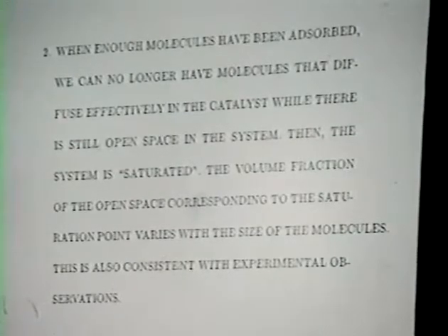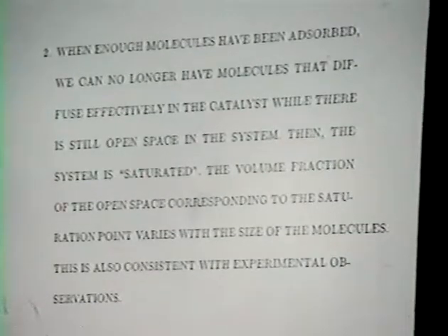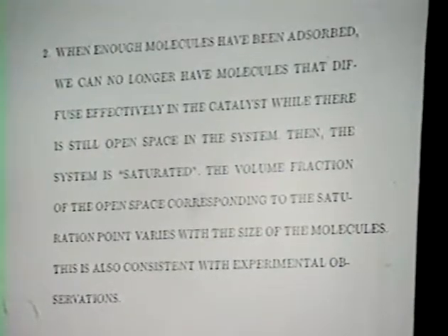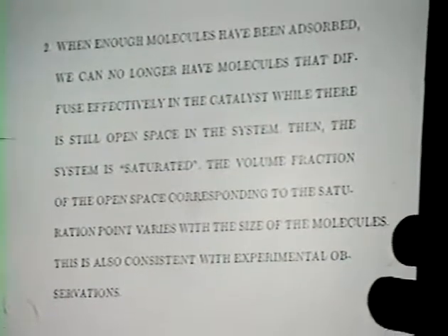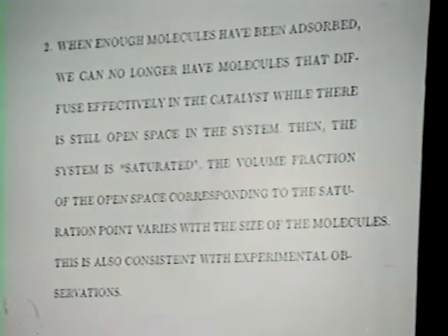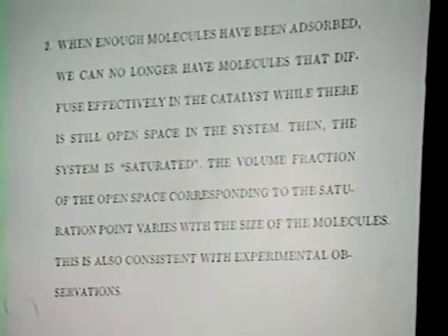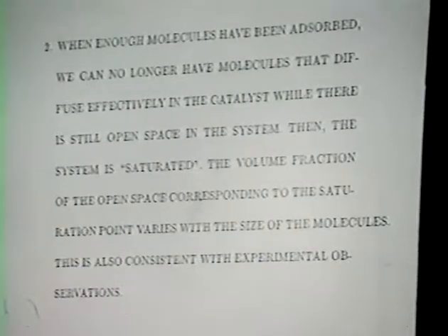There is another aspect of experimental data that I should mention, and then I'll finish my talk. When enough molecules have been adsorbed, we can no longer have molecules that diffuse effectively in the catalyst, even though there is still open space in the system, which means that the system basically has been saturated. The adsorbed molecules block the rest of the molecules from diffusing. And so we can calculate the volume fraction of the pore space at the end of the simulation which is still empty, but the system has been saturated.